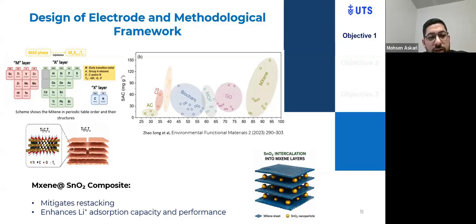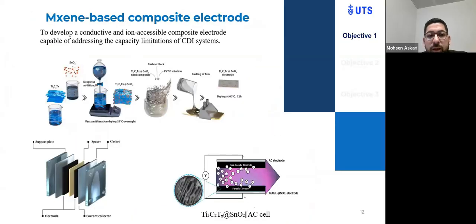It's a two-layer nanomaterial that has layer structures, but the main challenge is mitigating the restacking of the layers. There are some strategies to mitigate this restacking. One of the best methodologies is using a composite. Because of that, we use the MXene-SnO2 to mitigate the restacking and enhance lithium adsorption capacity and performance.